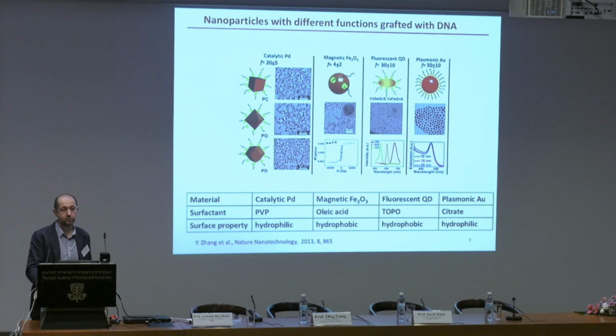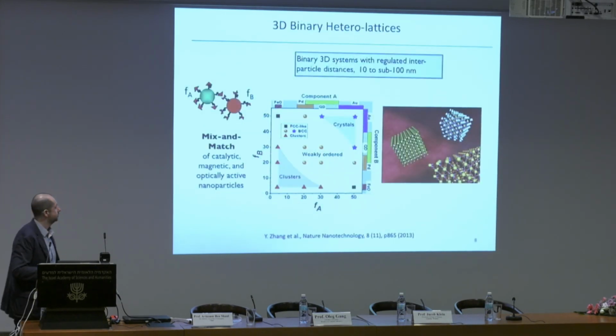You don't need to be limited to a system which contains only one type of particle. Essentially, we can mix and match, and different types of particles can be brought together in binary mixtures. This is more the material side of this diagram, and this is more the physical parameter space. From this side, we can, for example, take iron oxide particles and connect them with quantum dots, and you will have a system which might be optically active, but also responsive to the magnetic field. I'm not going to discuss all the properties which we investigated due to the length of the talk, but I wanted to stress there are many interesting opportunities for multifunctionality through mixing particles. In all those cases, we can change the interparticle distances from about 10 nanometers to somewhere in the sub-100 nanometer regime by simply changing the design of the DNA motif.